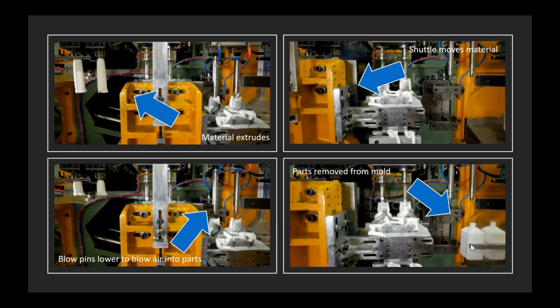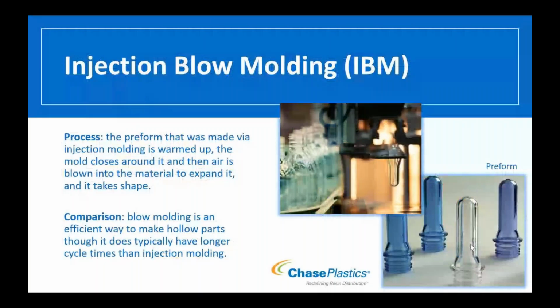So that's extrusion blow molding. Then we have injection blow molding. It's still a variation of blow molding, but instead of extruding the material out like we do for extrusion blow molding, we'll make what's called a preform first, and we do that via injection molding. These right here are little preforms that are made. These will become bottles, some form of a water bottle or some variant of it. This is made in a totally separate injection molding process first, and then they'll grab hold of it, heat it back up, blow air into it so it takes the shape of the mold again, and then the rest of the process remains the same.